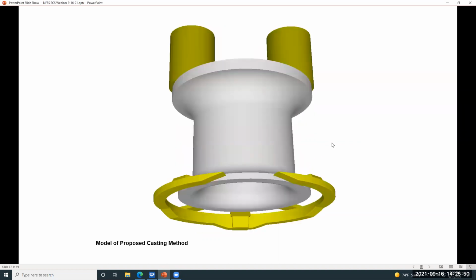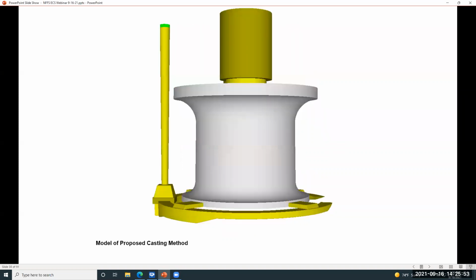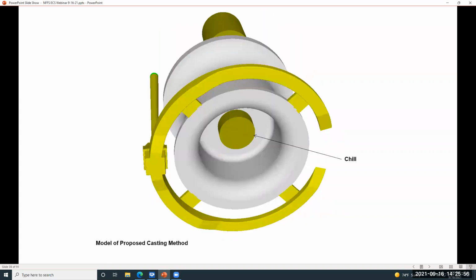This just shows another angled view. And this also shows that we'll be using a chill on the base in the center of the casting. The reason for this is with our initial simulation, we found that we could not get good feeding continuously through from the top riser down into the bottom part of the casting. So we used a chill to freeze off that area quickly and promote directional solidification.